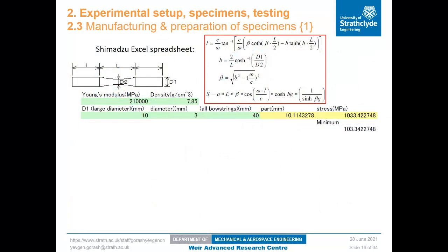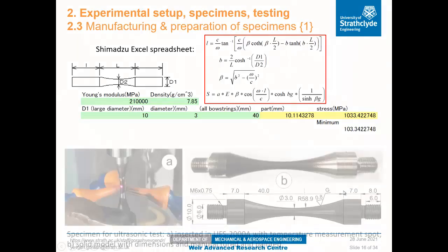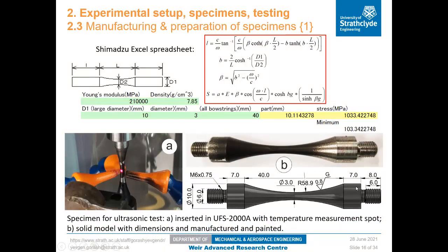Using the Excel spreadsheet provided by Shimadzu Japan and the material properties that we identified in our tensile testing, we managed to generate a correct geometry for the sample, so that the manufactured samples could resonate at 20 kHz. Another important thing is that a shiny polished surface has very low emissivity, and that's why, to improve the emissivity and temperature readings, all the samples except those that are pre-corroded were painted with black matte paint.